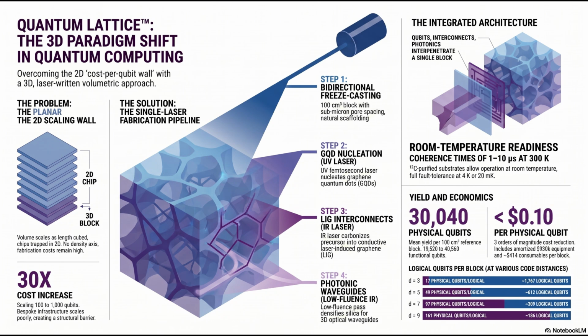Okay. Now, do you recall the polyamide precursor we mixed into the original soup? Right. The polymer that got trapped alongside the graphene oxide? I was wondering when that was going to become useful. The IR laser scans through the 3D volume, specifically targeting the regions coated in that polyamide. The intense localized heat from the high-fluence infrared pulses doesn't melt the glass. Instead, it carbonizes the polyamide. It burns it. It breaks down the polymer chains, boiling off the non-carbon elements as trace gases, and leaving behind a continuous, highly conductive trace of carbonaceous material. It is literally drawing electrical wires made of graphene directly into the aerogel matrix.